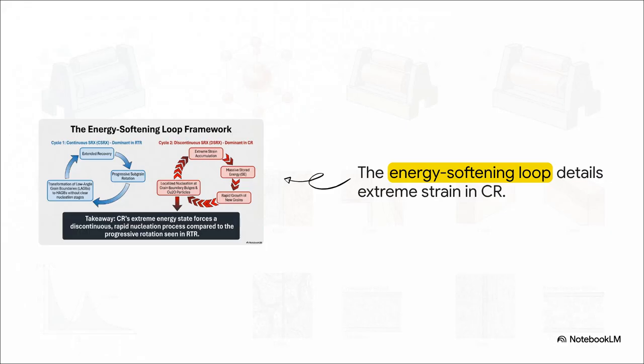When we map this all out into a complete framework, those two distinct pathways become super obvious. The continuous cycle for room temperature rolling shows this nice, gradual recovery. But looking at the cryogenic pathway, that extreme energy state totally bypasses progressive subgrain rotation. Instead, it goes all in on rapid, discontinuous nucleation directly at the grain boundary bulges. It is a fundamentally different mechanism for structural relief.